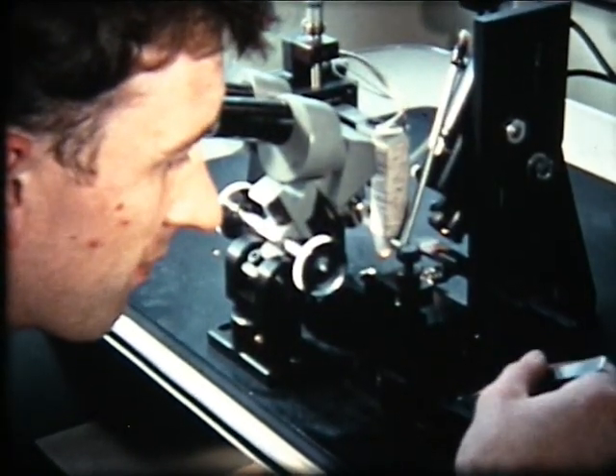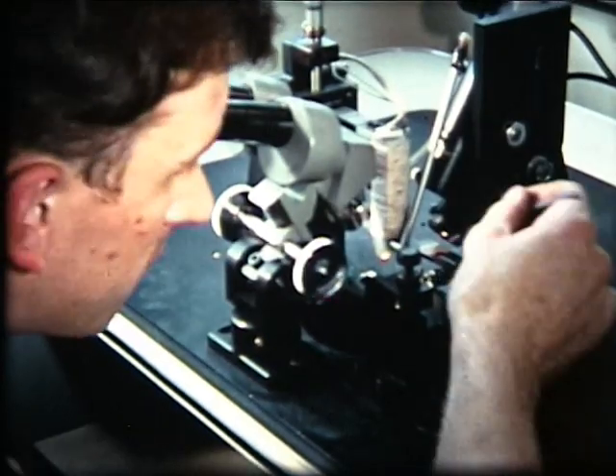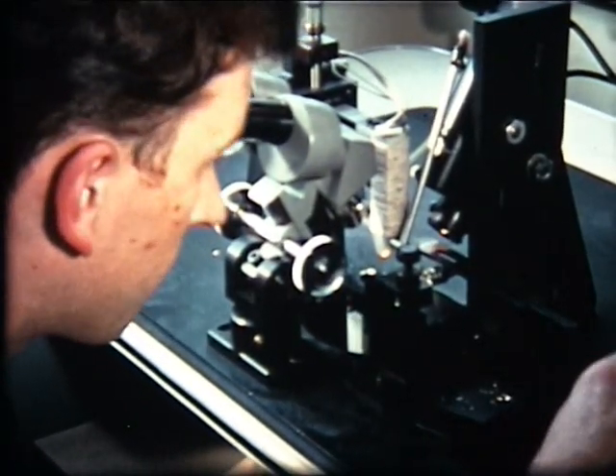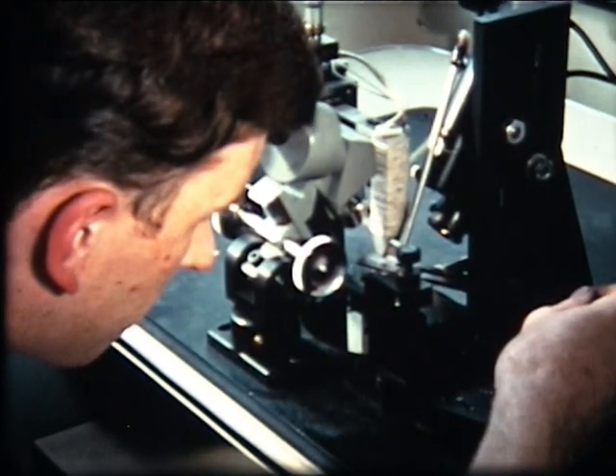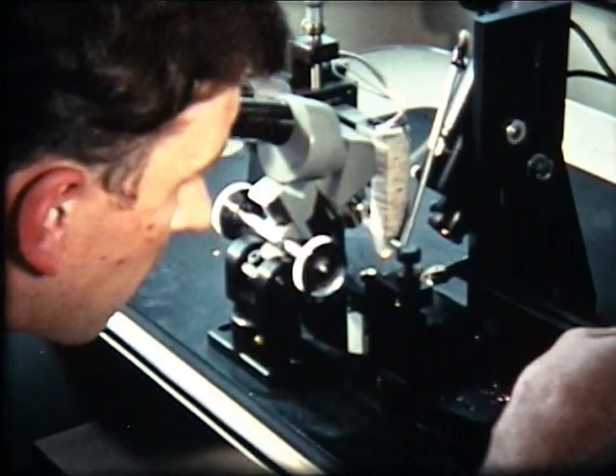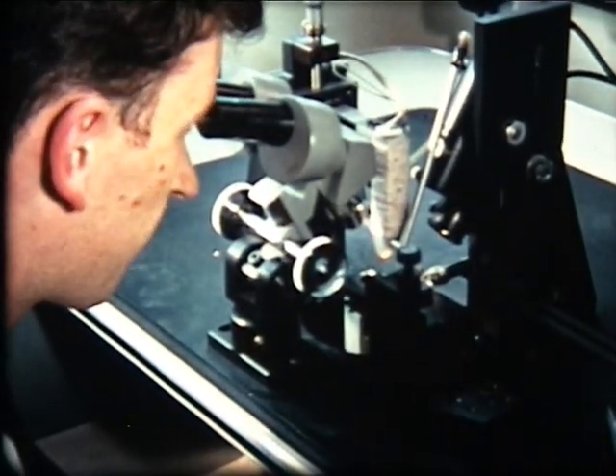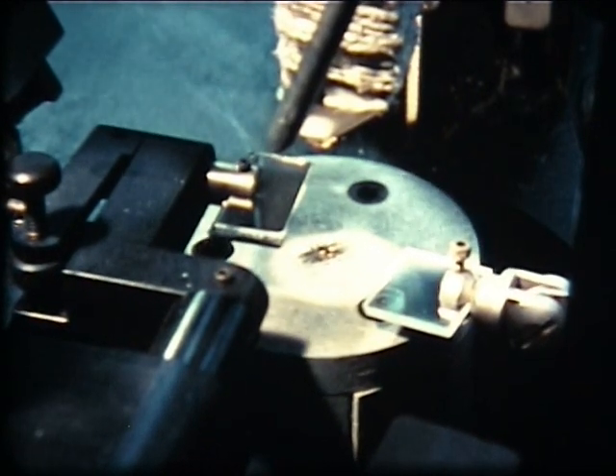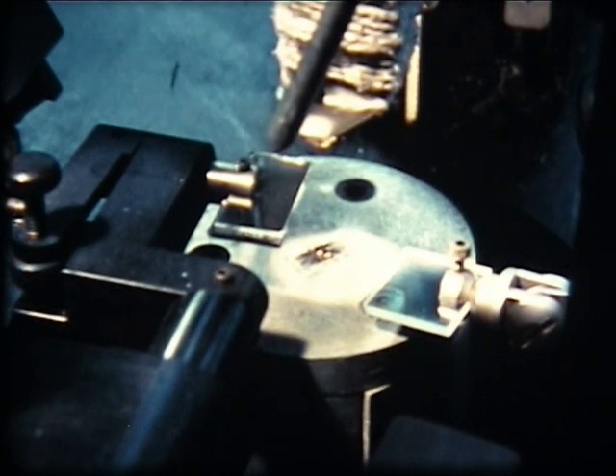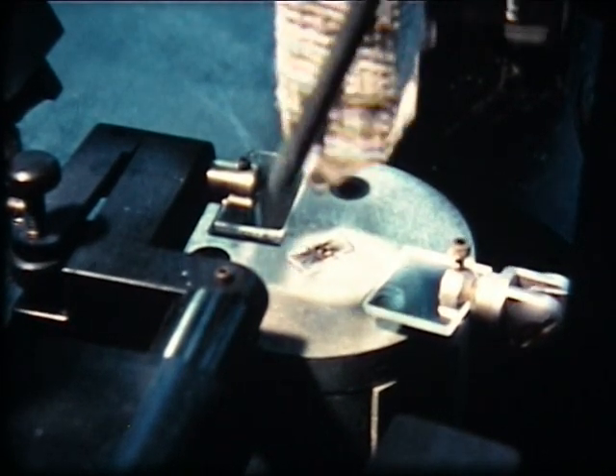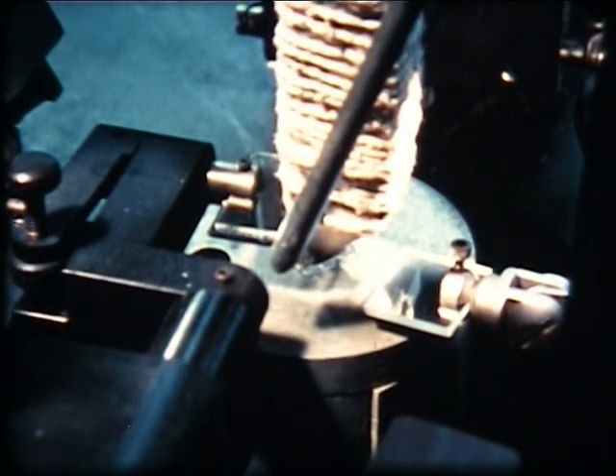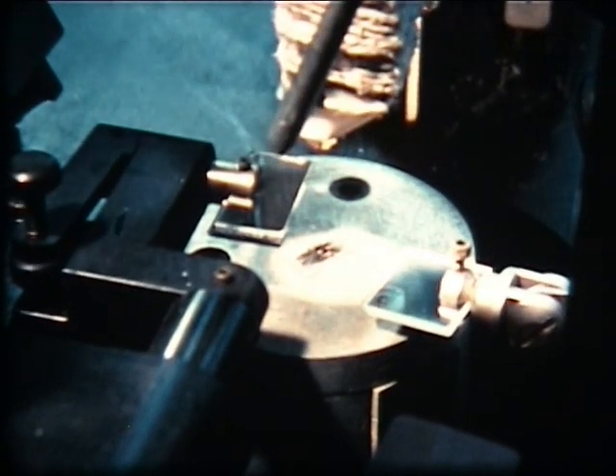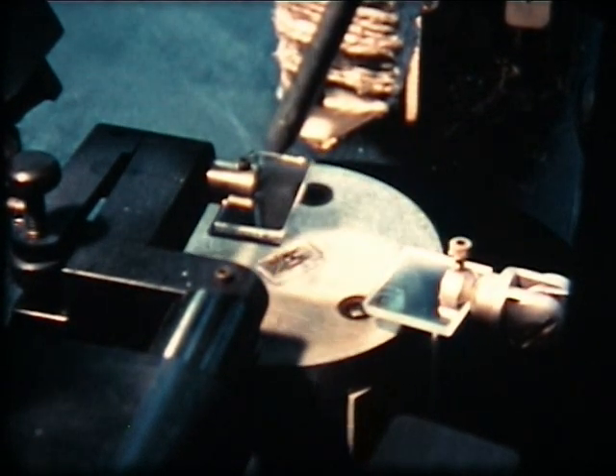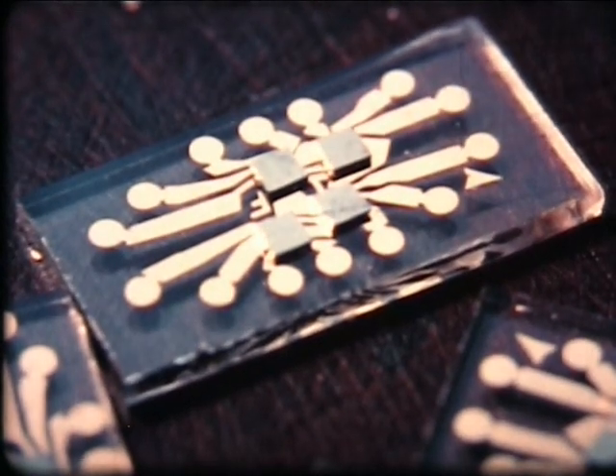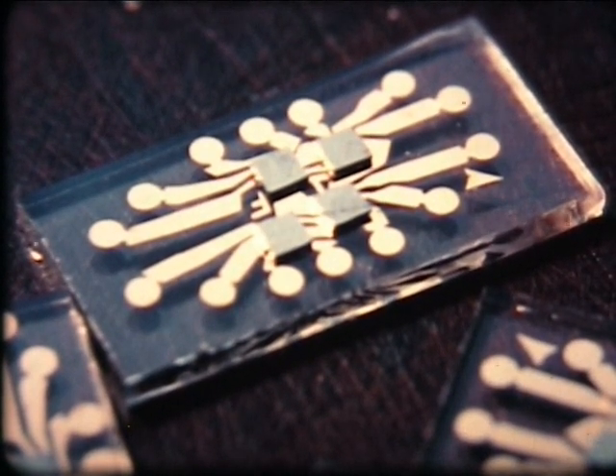Another way of marrying silicon chips and thin film elements is practiced at the Wythenshawe laboratories. Through his microscope, this operator sees 2 images superimposed, one of a specially prepared thin film circuit, which is face up, the other of a silicon chip suspended above this, face down. The thin film element is moved by delicate controls until the image of a prepared area on its surface coincides exactly with the image of the chip. The chip is brought down into contact with the glass substrate, and heat and gentle pressure bond corresponding contact points together without the use of connecting wires. Several chips may be used in each flip-chip hybrid circuit. A view through the reverse side shows the chips and connections.